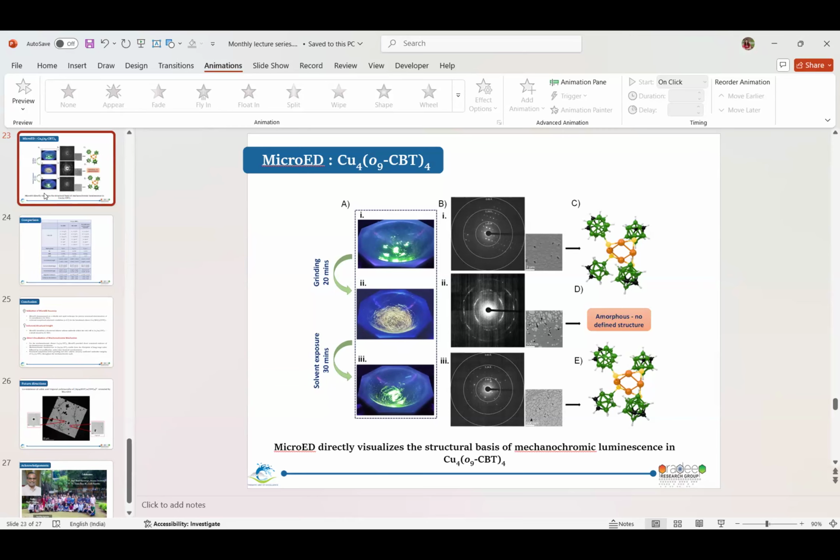There might be something else playing a role, because of the mechanical stress also which we are applying. Can it depend on that as well? Yes, it is possible, indeed. And secondly, when we are heating it, we are not changing the size of the crystal. So a smaller surface area will be exposed to the vapor, and it might take a very long time to come back to green. That is also an explanation. But I really feel there is something else other than only solvent.